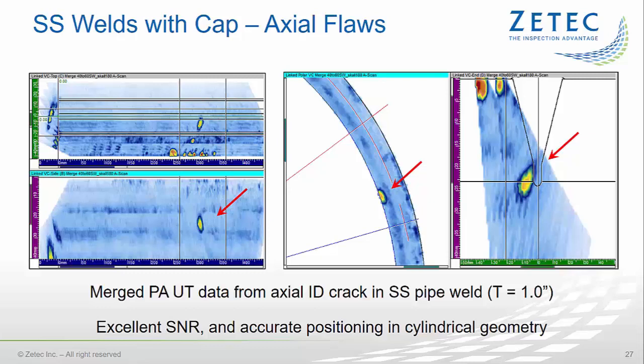The actual positions of the two scan lines are determined as a function of the pipe thickness and the weld crown width. The first scan line, as close as possible to the weld crown toe, aims for flaws located near the weld root, and the second scan line completes the coverage of the heat-affected zone. The footprint of the probe is optimized to bring the beam exit point as close as possible to the weld crown toe without generating major internal reflections in the wedge.